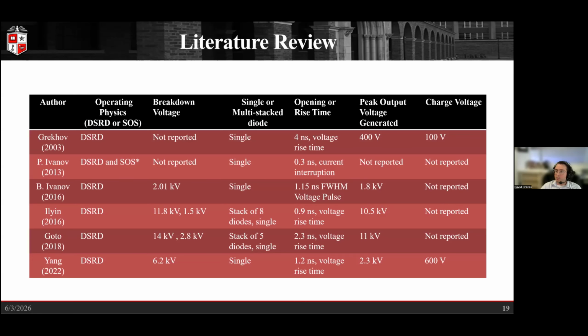So highlighting some of the previous work that we've looked at in the literature, as I mentioned, a lot of the SOS work was on silicon. So for comparison, we're trying to look at some of the silicon carbide devices, and most of them end up being purely for DSRDs, so the much faster but lower power capability devices. We can see the voltage levels that we're looking at. In most recent years, we've had a single device that goes up to 6.2 kV. In this one, they're doing 5 stacks of dies to get a total package device of 14 kV.